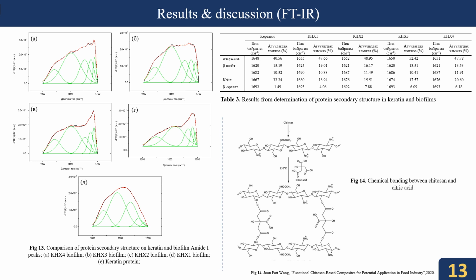So during biofilm formation, the proportion of the protein alpha helical structure increases, and the amount of alpha helical structure is highest, around 53%, in the case of keratin content of 15 and citric acid content of 10. The alpha and beta structures of proteins are stabilized by the hydrogen bonds between amine and carboxyl groups in the polypeptide chain. Through the hydroxyl group of citric acid, the carboxyl and amino groups of natural polymers and proteins are additionally connected to form stable secondary structure of proteins.